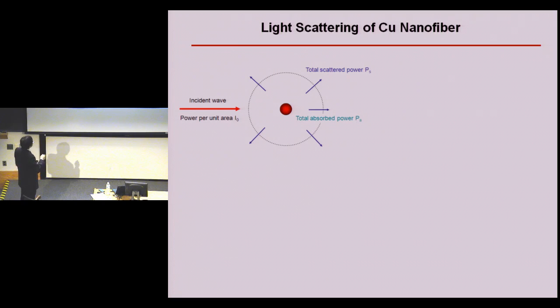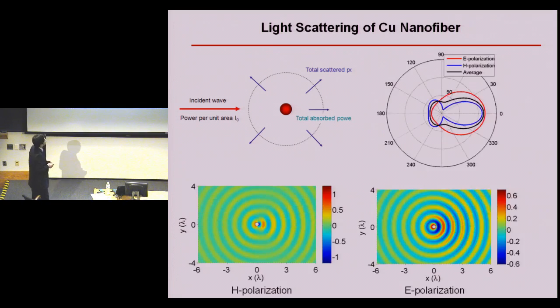So I did some simulation for understanding the fundamentals of the scattering. So here, this is the cross section of a copper nanofiber. The incident wave coming from the left side is a plane wave. And we assume there are two polarizations. One is the E polarization, that means the electric field is along the direction of the fiber. The other one is the H polarization, that means the H field is along the fiber. So the black curve shows you the intensity distribution of the average of the two polarizations. So you can see here, this is the forward direction. So indeed, there's a large portion of the light which is scattered off the zero direction.